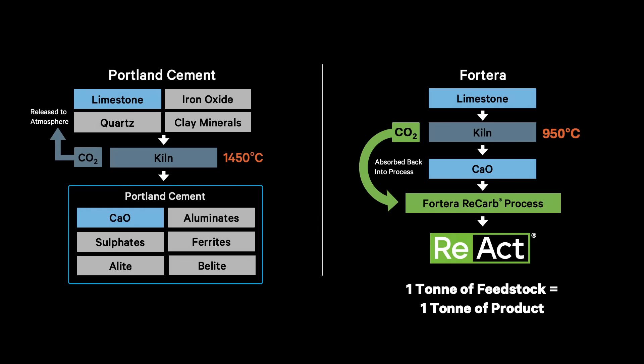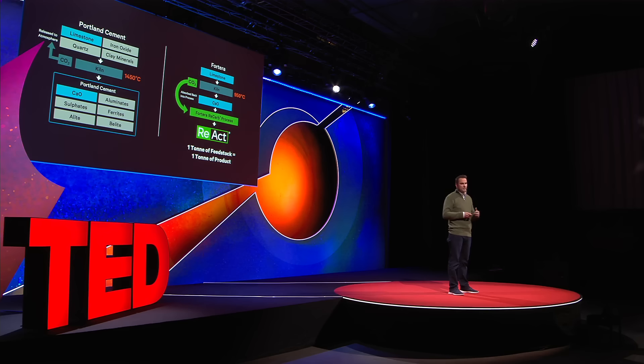What we figured out is we could take that technology and put it at existing cement kilns alongside existing cement manufacturers. In doing so, we can bolt onto the back of the process — capture the CO2 gas coming out of the kiln with the lime we produce from that limestone — and produce a product that can then be blended with traditional cement or utilized as 100% cement replacement. By capturing that CO2 and turning it back into a product, we effectively double the amount of product we make, which is what makes it economically competitive. So a little bit comically, we're taking limestone and turning it back into limestone — but going from an inert rock to a form of limestone that is actually a cement. In doing so, we're able to reduce CO2 emissions by 70% per ton when still using fossil fuels, and if we integrate with clean electricity or green fuels, we get all the way to a zero CO2 cement.